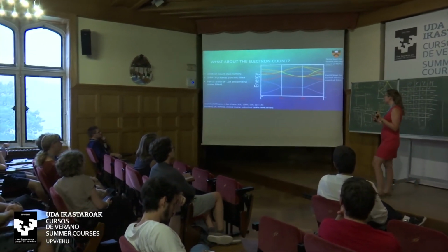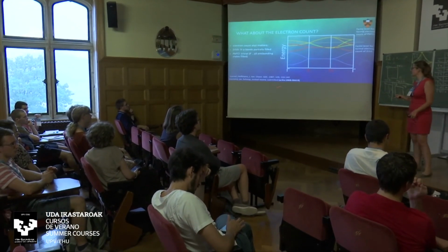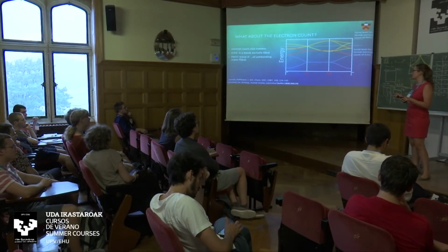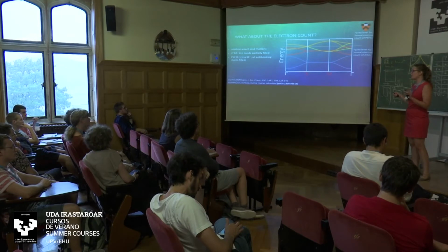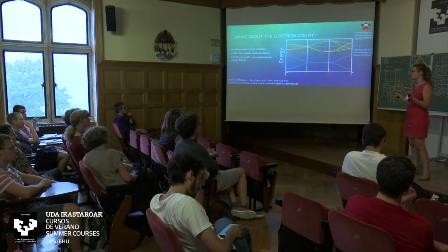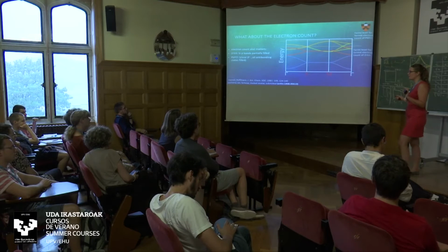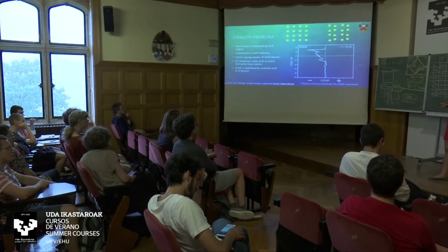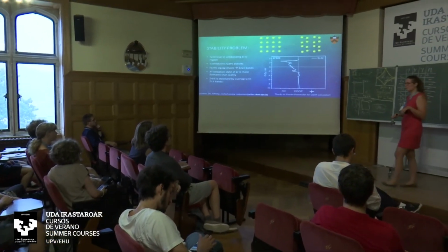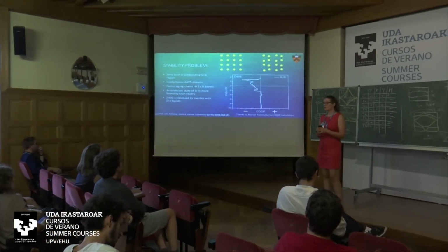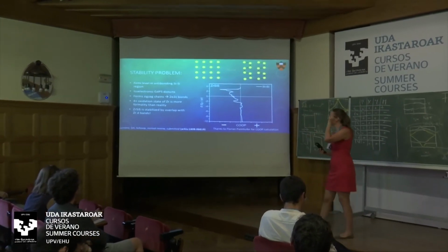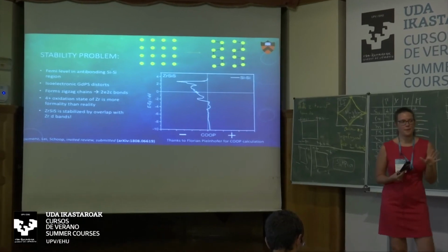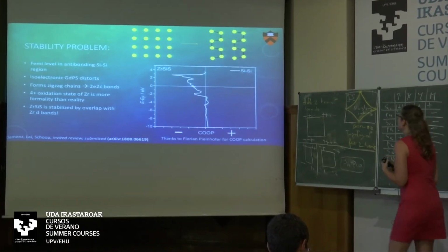Okay, so because we have 6 electrons per silicon, that means we fill the full S band, so it's folded, so just divide by half, right? We fill the full S band, we fill the full PZ band, and we fill half of the PX and the PY, right? So we have a half-filled band here. I'll come back to this later. This is actually a very special thing. Actually, good point. Because a half-filled band is a problem, and therefore these materials also have a stability problem. So tomorrow, or maybe later in this lecture, I forgot when it's coming, I will talk more about half-filled bands, which are actually rare to happen. Yeah? 5 more minutes. Oh, okay, so I don't know if I will get to this at all.